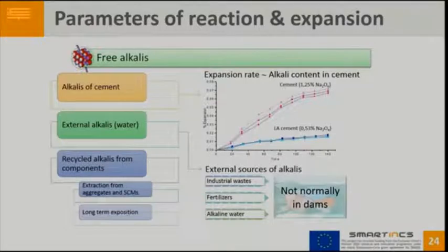But also some aggregates, such as feldspars and other particles, can release or leach some alkalis, contributing to the alkali silica reaction.